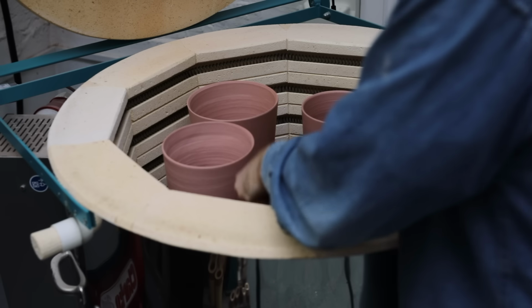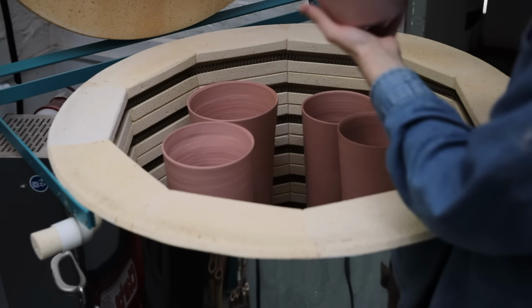Sadly, I destroyed one of the pots, placing it inside the kiln. I knocked one corner of it against the interior brickwork, and it caused one portion of the very thinly turned wall to fracture, so that's one lost. Hence why there are only 5 going in instead of the 6 like there were. Sadly too, another one of these pots had a giant S-crack form in the base after it had been fired, which meant that only 4 of these were any good to continue with.